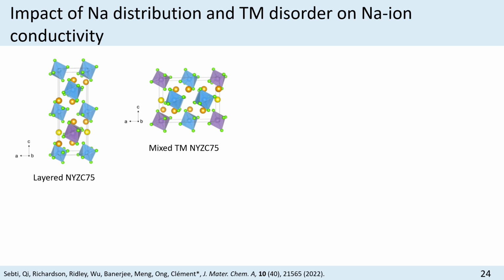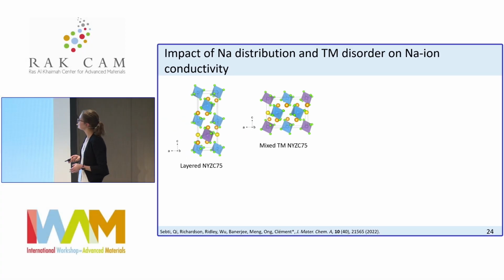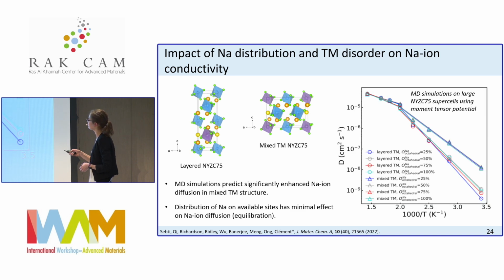We wanted to understand a bit better what's the impact of the distribution of sodium in these prismatic and octahedral sites on sodium conductivity, and what is the impact of transition metal disorder in the mixed yttrium-zirconium system. So here we collaborated with the group of Shuping Ong at UCSD, and we looked at diffusion in a model where you have layers of yttrium, and then you've got layers of zirconium alternating. So this is a fairly ordered structure. This is a more mixed structure. And we looked at the impact of these two models on the diffusion properties.